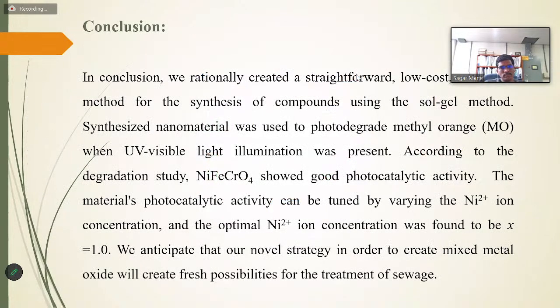In conclusion, we realized that we rationally created a straightforward, low-cost, novel method for synthesis of the compound using the sol-gel method. The synthesized nanomaterial was used to photodegrade methyl orange in the presence of UV-visible light illumination. According to the degradation study, the NiFeCrO4 compound shows good photocatalytic activity. The material's photocatalytic activity can be tuned by varying the Ni+2 ion concentration, and it is optimum for a particular Ni+2 concentration. We anticipate that our novel strategy to create a mixed metal oxide will create fresh possibilities for the treatment of the sewage.